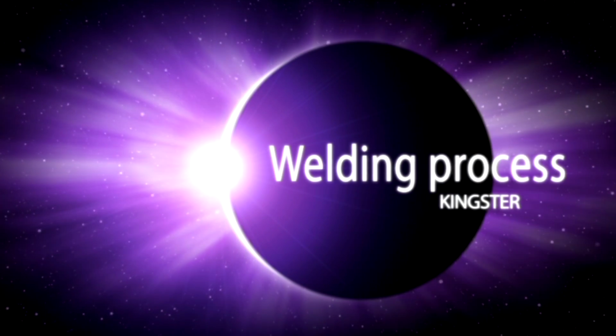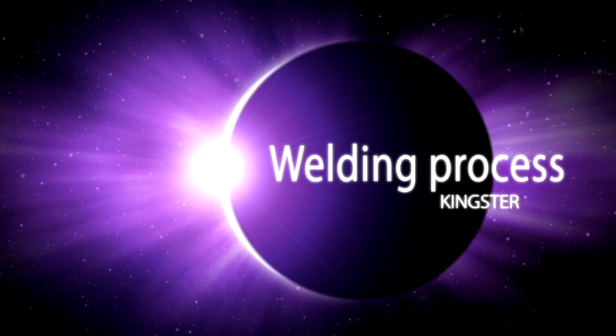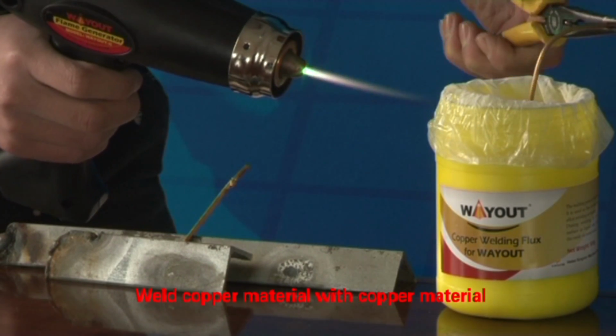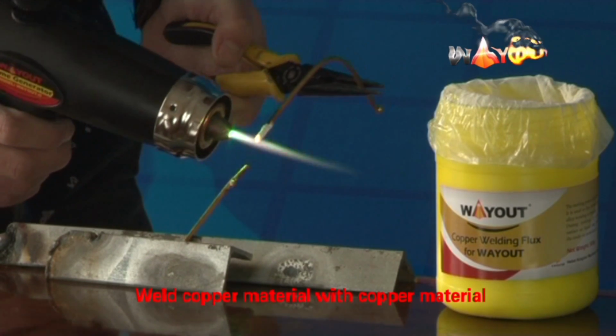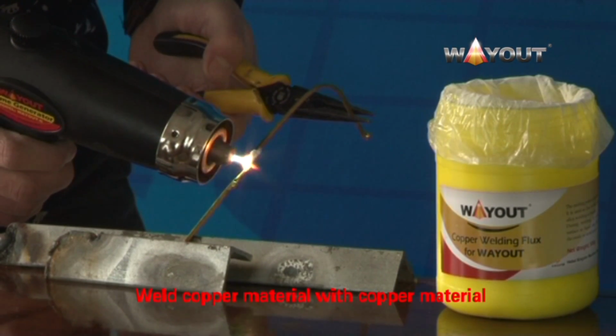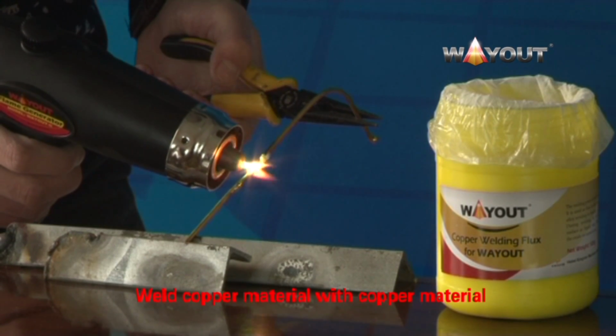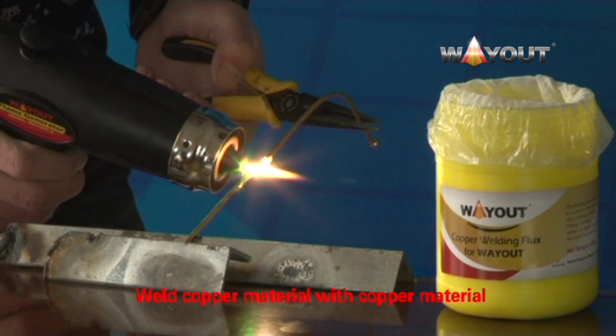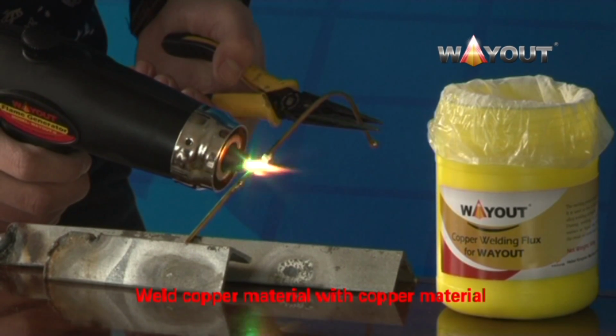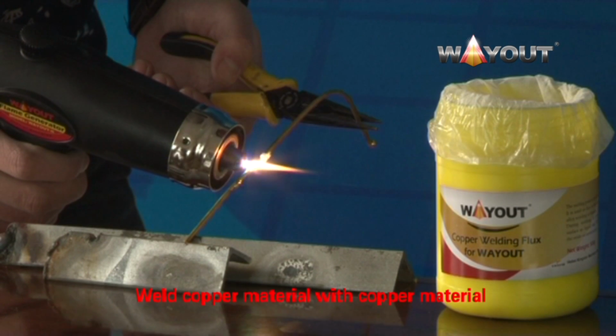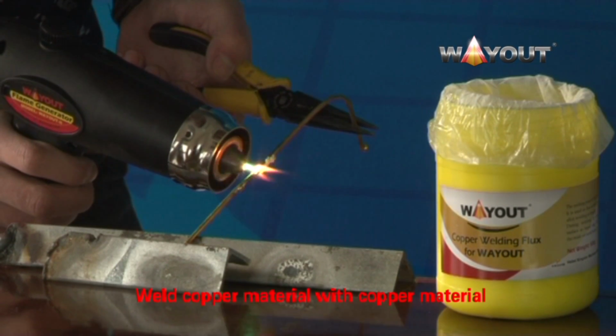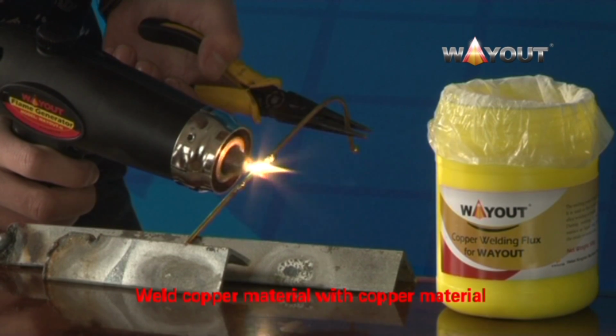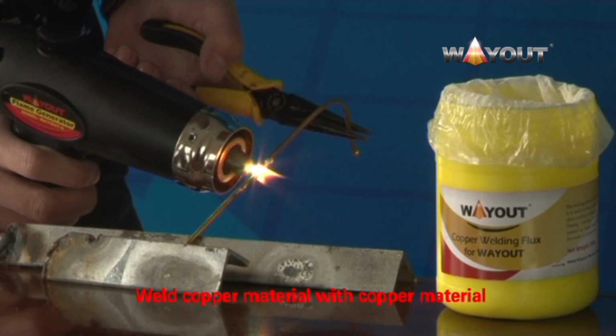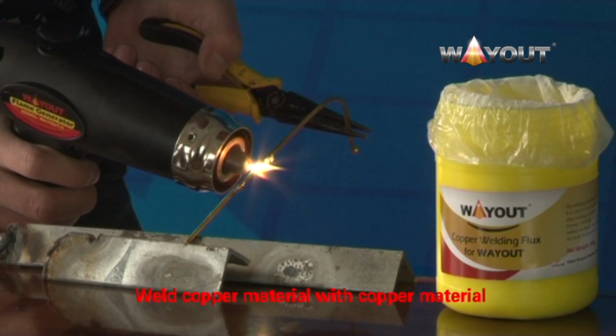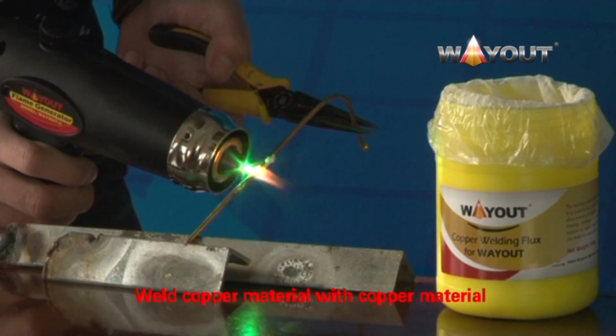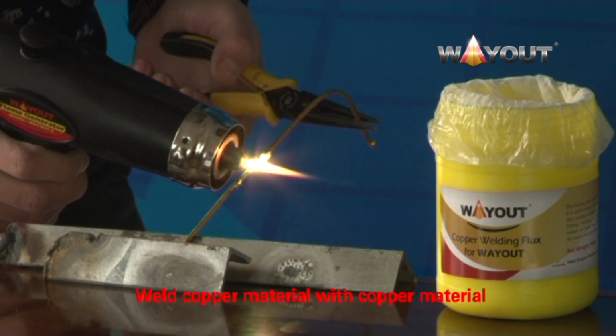4. Welding process. 1. Weld copper material with copper material. First, heat the workpiece and dip the part to be welded into welding flux. The melting point of this flux is about 650 degrees Celsius. It is used as flux in copper and copper alloy welding or brazing. During welding, it covers the welded surface as liquid slag, effectively dissolving the oxide on the metal surface. The welded workpiece is clean, bright, and solid.